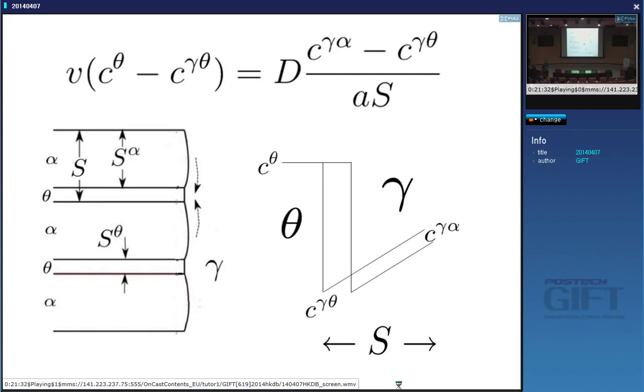But in addition to growing the phases, what are we doing? What else are we creating? So we are creating volume fractions of ferrite and cementite, but what else are we creating? Interfaces, yeah. Exactly. So these boundaries have energy. And if you make your spacing finer, the pearlite can grow faster according to this equation. If I make the spacing zero, it will grow at an infinite rate. That's because we are ignoring the creation of interfaces. So we've got to allow for that.